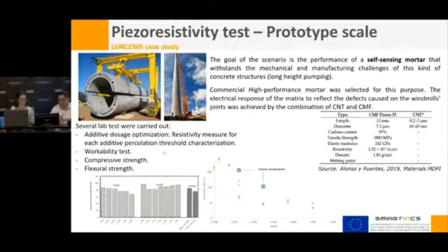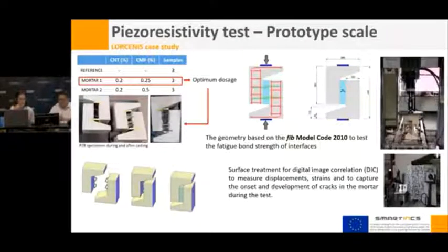We also made workability tests because, as Javier has told before, it was very challenging, mainly because of the formation of bundles with carbon microfibers, more than with carbon nanotubes. And also compressive and flexural strengths. As you can see here in the graph, in our case we didn't see a very significant improvement in these strengths when using carbon nanotubes and carbon microfibers. After the laboratory results, the optimum dosage selected for the prototype scaling was 0.2% carbon nanotubes and 0.25% carbon microfibers by weight of cement. I didn't reflect it here, sorry.